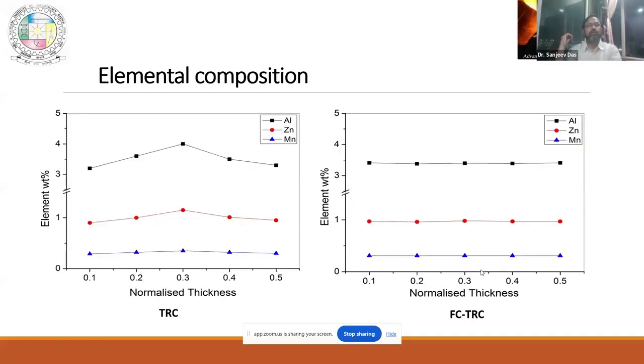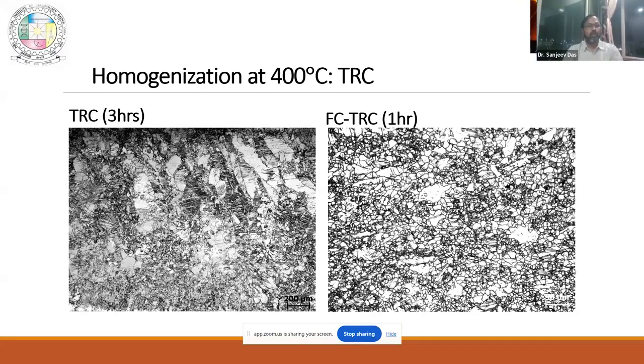If you see the elemental composition, there is a lot of segregation in the case of twin roll casting at the center, but it is quite uniform for the forced convection twin roll casting. Now about homogenization. We tried to do some homogenization of these strips. After 3 hours of homogenization, we still find some bigger grains in the twin roll casting. But after just 1 hour, you get a very fine equiaxed structure in the case of forced convection twin roll casting.